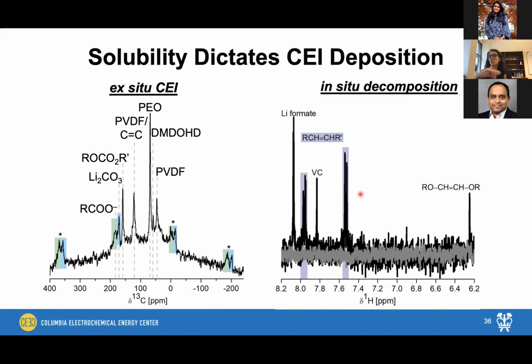So they're depositing on top of that lithium carbonate and the lithium fluoride. They're also depositing on the surface of our carbon additives, so on top of our conductive carbon and on top of our PVDF, sort of giving this false notion that the carbon additives might be playing a role in producing these molecules, but they're actually just these soluble components and they don't really care what they stick to at the end of the day.